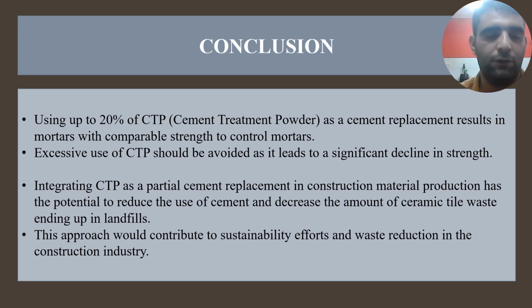At the end, conclusion. Using up to 20% of CTP, ceramic tile powder, as a cement replacement results in mortar with comparable strength to control mortar. Excessive use of CTP should be avoided as it leads to a significant decline in strength.